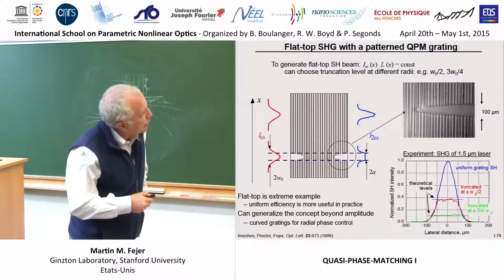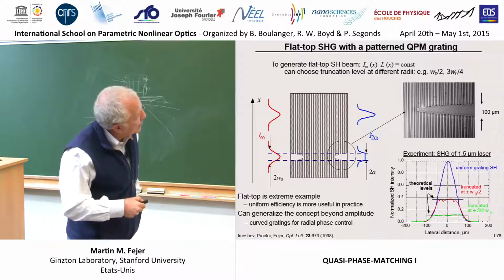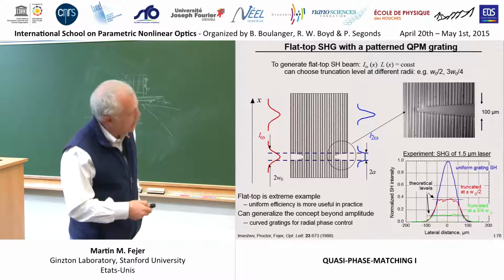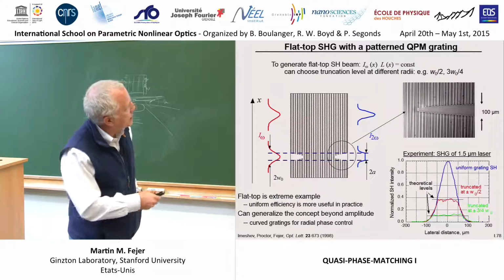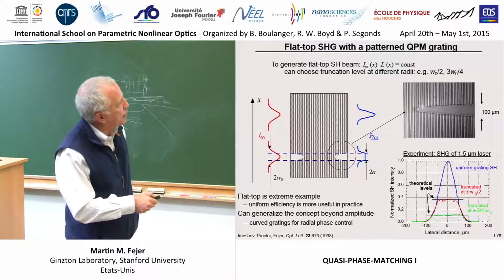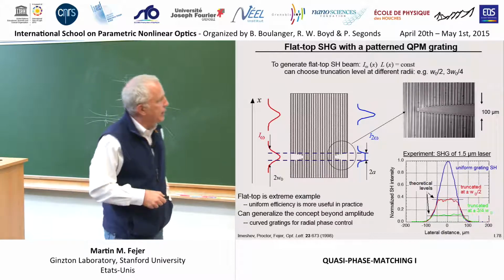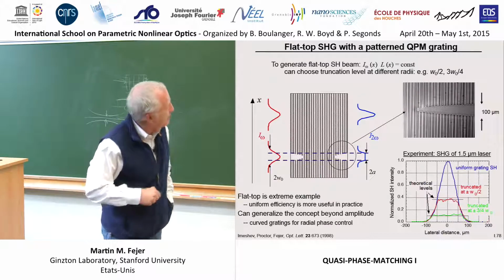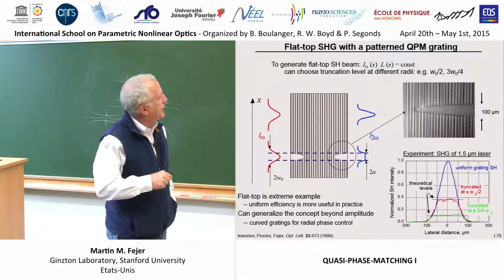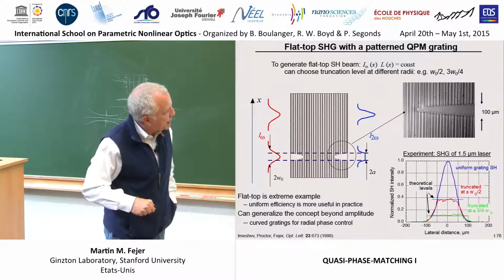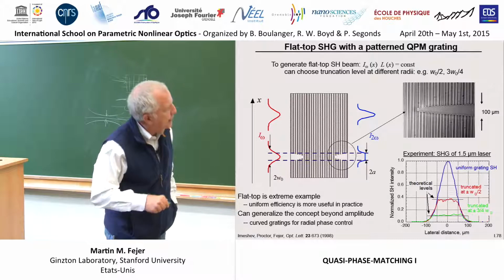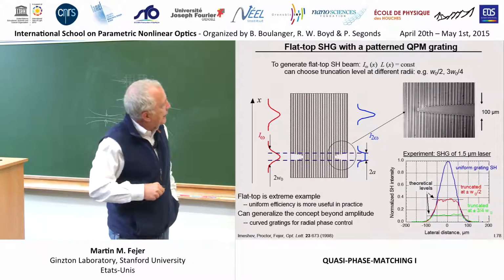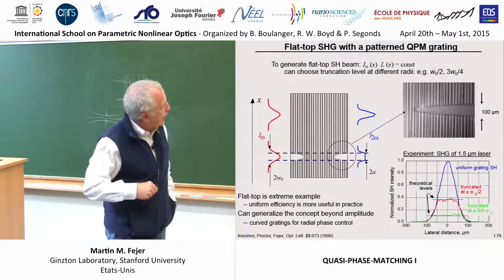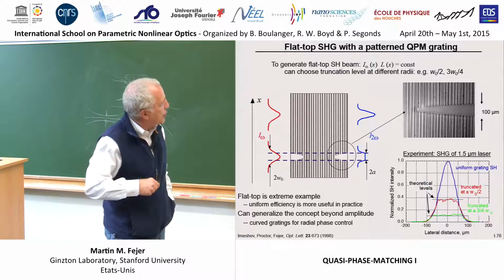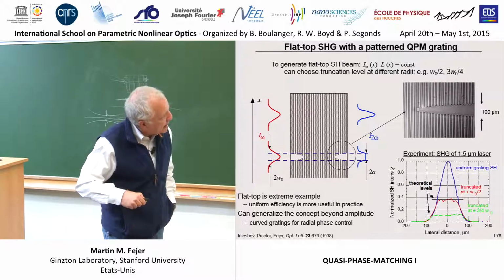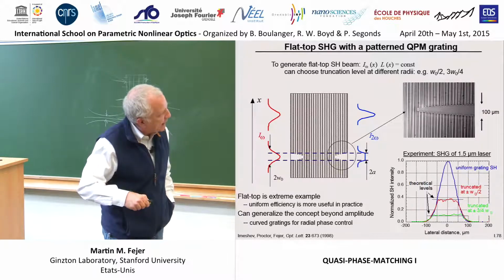So this is a micrograph of a 100 micron such region designed for a particular size of Gaussian beam. And here you see an experiment where first it was done in a uniformly poled section, and you see some SHG efficiency here. That's a Gaussian, as you would expect. And then in this flattened region, making 2 different choices of how wide a region across the Gaussian to flatten. Instead of seeing this, you see a flat and a flat.